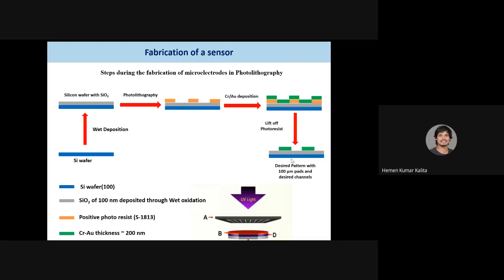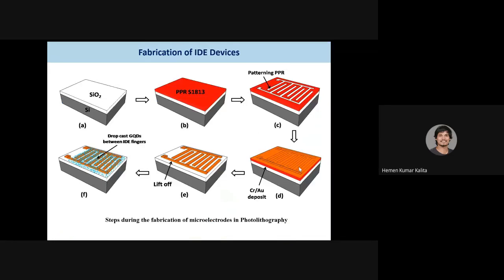So that means we can get desired patterns on the top of silicon and silicon dioxide. So you can fabricate any kind of structure depending on your mask design. You can fabricate square, you can fabricate smaller square, bigger square. Here, in this particular case, we have tried to fabricate 100 micron square pads. In this diagram we have shown that. Now, for sensors we have used a similar technique, but we have not used pads. We have used IDE structure.